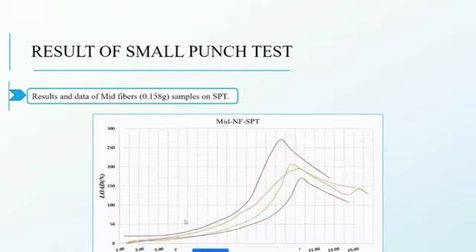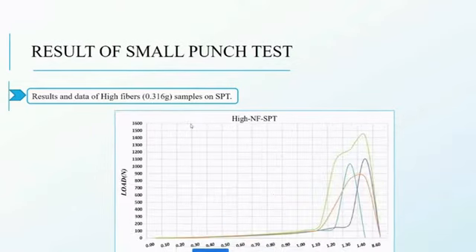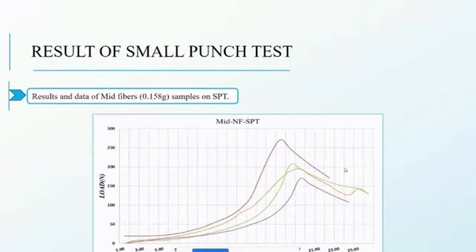For the medium, when we add more fiber, we notice that it is following the same trend, except that at the peak there is no more resistance. The sample starts to fracture, which shows that we start to create internal cracks. The fibers act as internal cracks as we add more. So there is an optimum amount that we should study. Even for the high one, adding more fiber, we start to get a high peak, which is very good, but at the end it starts to fracture. There is no more resistance at the peak when it starts to fracture compared to this one.